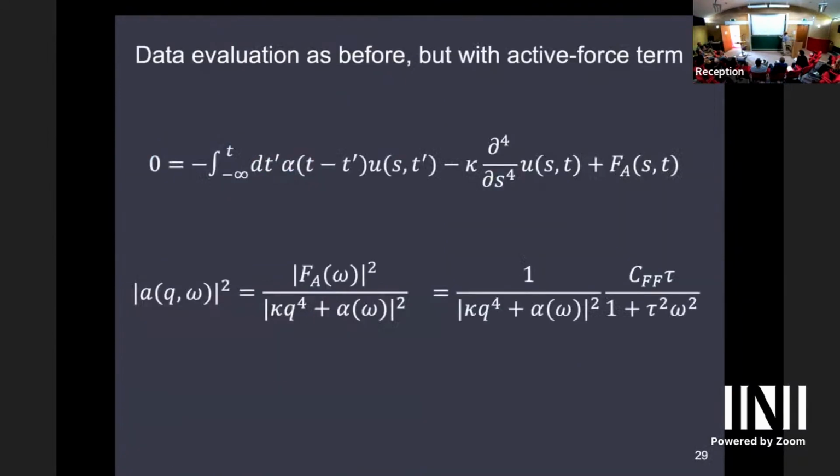But now we have to add one more force. So there's an active force coming, of course, from the myosin actin again, that we have to take into account. That's bending. Actually, that's the one that's really mostly bending the microtubules. The thermal fluctuations are almost negligible. So we again look at the mode decomposition, and then now have here, of course, the force including or dominated by the active force.